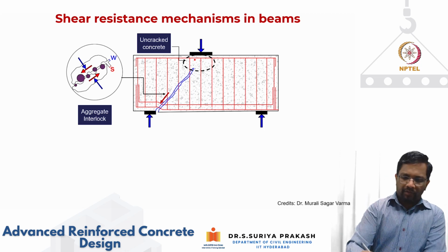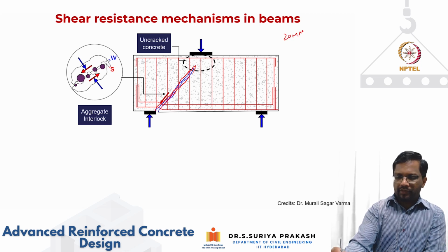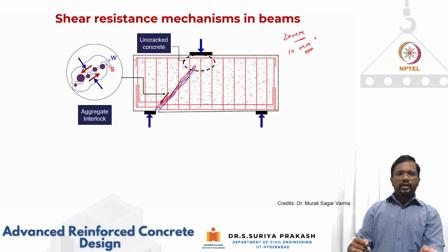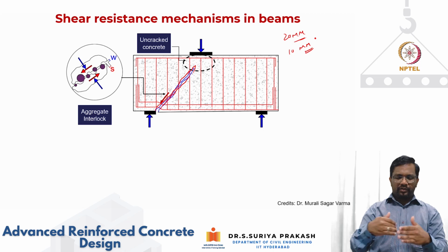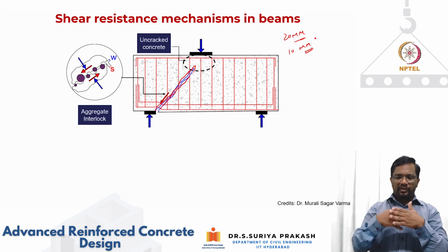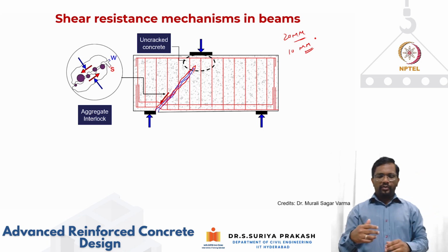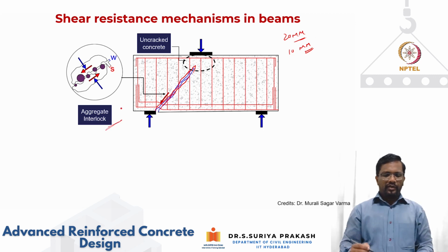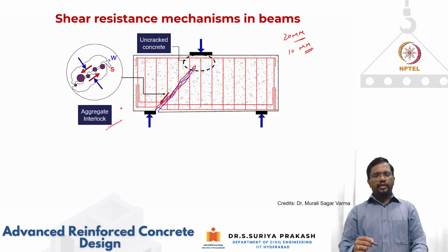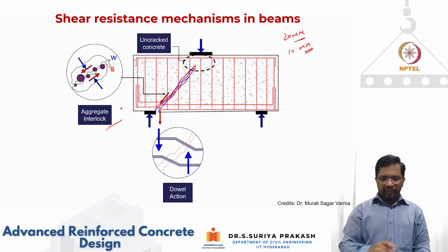And then once the crack is formed, the crack surfaces are going to be very rough, because you're using, let's say, a 20 mm aggregate or a 10 mm aggregate in SCC or microconcrete. So the crack will basically go around that aggregate. Now when these two rough surfaces are sliding against each other, you're going to generate a lot of resistance in shear. This phenomenon we call aggregate interlock.